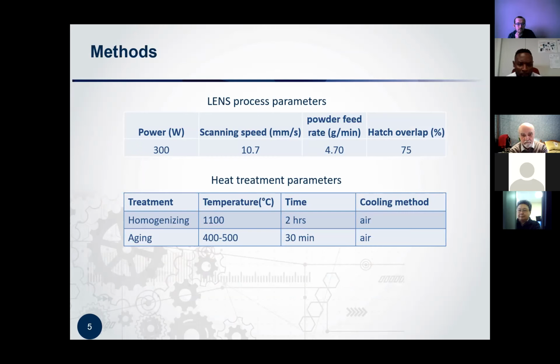For us to build the samples, as I said before, we firstly optimized the parameters for the lens, and we were able to come up with this set of parameters. We had, I think, 36, but we were able to come up with these lens process parameters: 300 watts, a scanning speed of 10.7, a powder feed rate of 4.7 grams per minute, and the overlap was 75%.